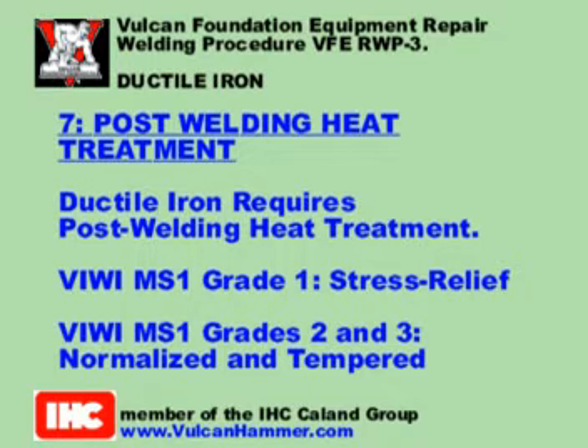Material poured to specification VIWI, MS1 Grade 1 need only be stress-relieved, while VIWI, MS1, Grades 2 and 3 material should be normalized and tempered. The recommended heat treatments are as follows.